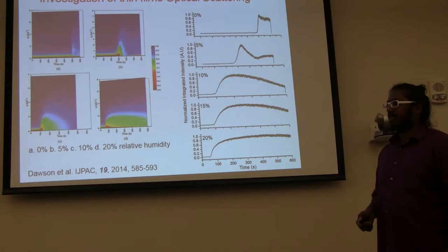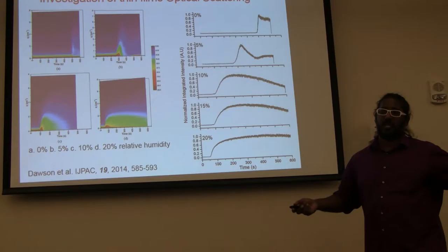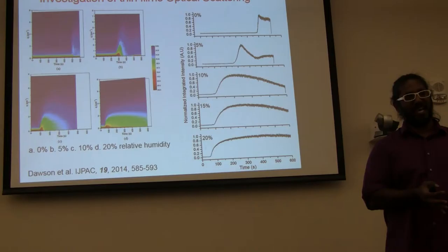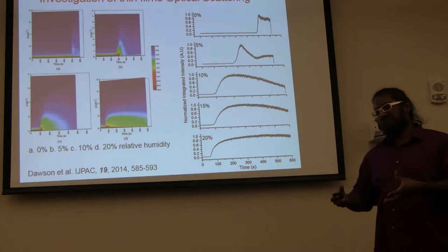So these are the final charts. This is the intensity plot where the color indicates intensity. This x-axis is the time that's been spinning. And this y-axis is something that we call the scattering vector. The scattering vector is basically something that tells you about the size of whatever is causing light to go off in different directions. What you have to know about this is that smaller numbers mean that there's larger objects and higher numbers mean that there's smaller objects that are scattering.